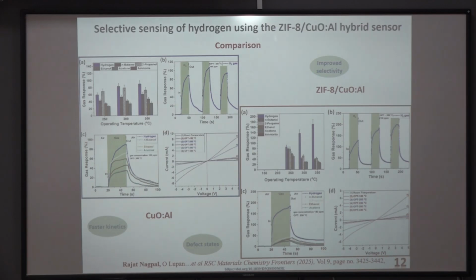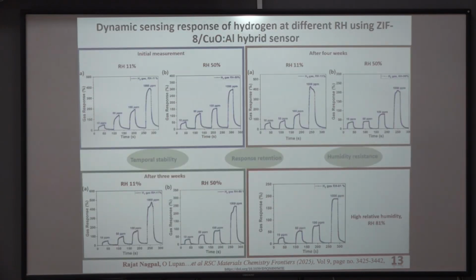Coming to the application part for the sensing performance, here we can see going from bare metal oxide to the developed hybrids, there is appreciable improvement in selectivity for hydrogen sensing, and using the dynamic sensing curve, here we can see it gives insights about faster kinetics, and using current voltage characteristics, it shows linear behavior, it follows Ohm's law. But at high temperatures, there is slight deviation from linearity, which could be attributed to the defect states.